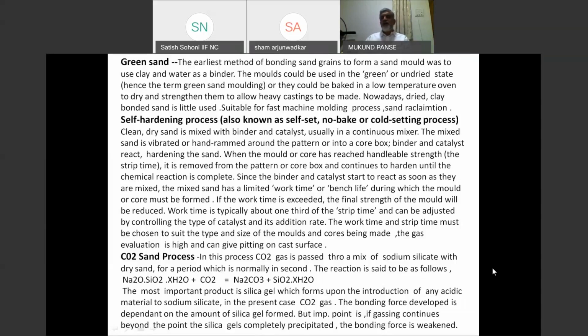However, at around 500 to 600 degrees centigrade, the CO2 sand mixture forms a meshy zone, which is not very hard. If your sand is not going to reach a temperature beyond 500 or 600 because of the configuration of the casting, you can use CO2 sand without any problems of collapsibility, and you can have savings also in this. However, reclamation of CO2 sand is very difficult. CO2 sand can be completely reclaimed only by the wet process, that is washing of the sand, which is now practically impossible with the quantity of water required.